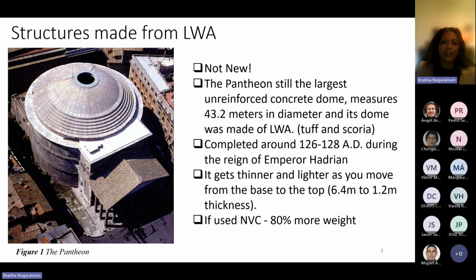So how they built and how they envisioned the construction was the dome itself, it got thinner as it moved up from the base to the top. So the base here is 6.4 meter in thickness, and towards the top it's 1.2 meter in thickness. At the base the material was made with travertine, and at the top it's made from tuff and scoria. There was an analysis done, and if this same dome was made using normal weight concrete, it would probably weigh 80% more, and it would require reinforcement. So like I said, the Romans built this without any reinforcement, and it's still the largest unreinforced concrete dome in the world.